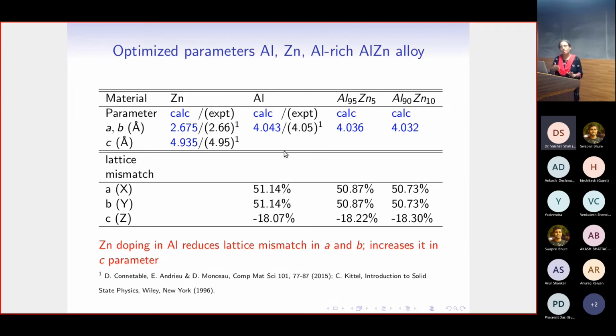So now if I want to construct an interface, I have to put two surfaces together, and because we know that these are two materials where they have a significant amount of difference in the lattice parameter, we calculate what is the lattice mismatch between the zinc and aluminum. So we see that if I were to interface pure zinc with pure aluminum, then in the A direction I have a 51% lattice mismatch, B direction same amount of lattice mismatch, and for the C parameter I have 18% lattice mismatch.